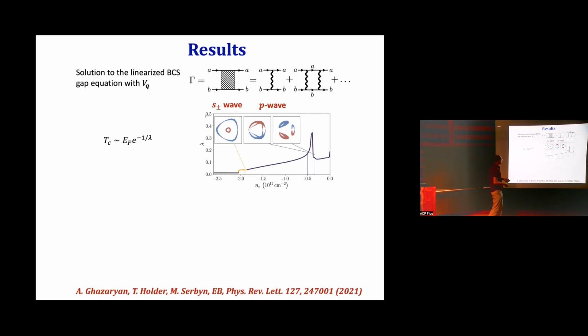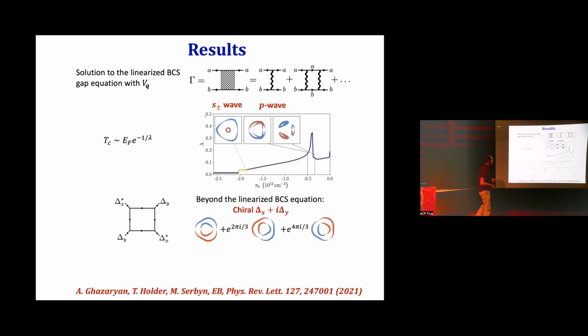But the interesting thing is that over most of this density range, the pairing symmetry is P wave. It's P wave like, not S wave. And moreover, if you have P wave, you have two degenerate pairing states, Px and Py, and they have to decide how to combine. They turn out to combine in this chiral combination, Δx + iΔy. That means that the Cooper pair actually breaks time reversal symmetry. This means that the Cooper pair is actually spinning spontaneously. So this superconductor is behaving in some way like a magnet. Every Cooper pair has a magnetic moment.